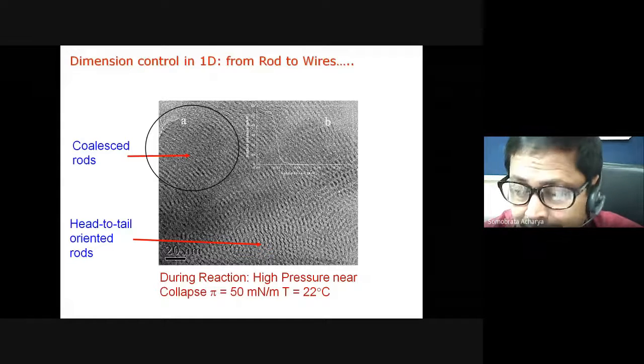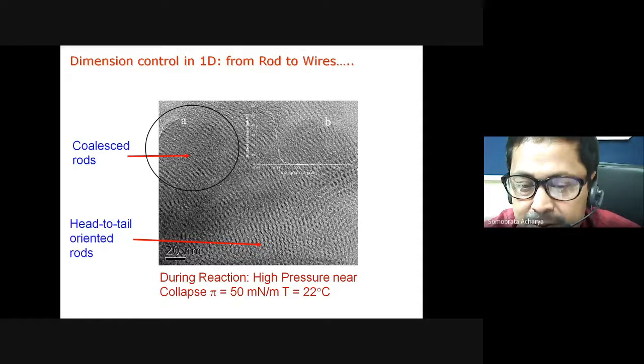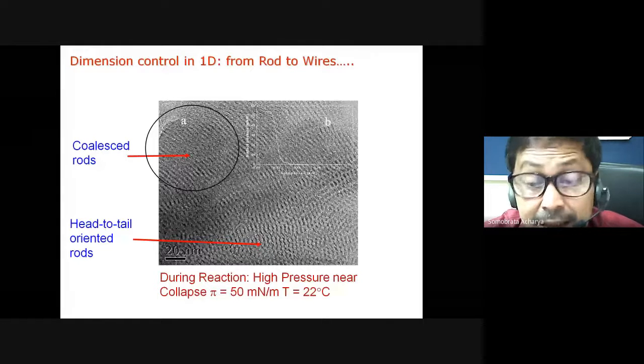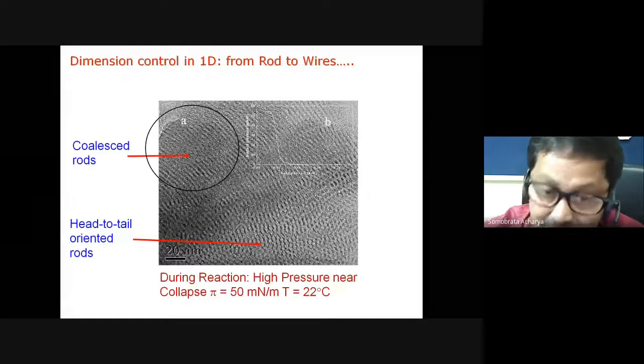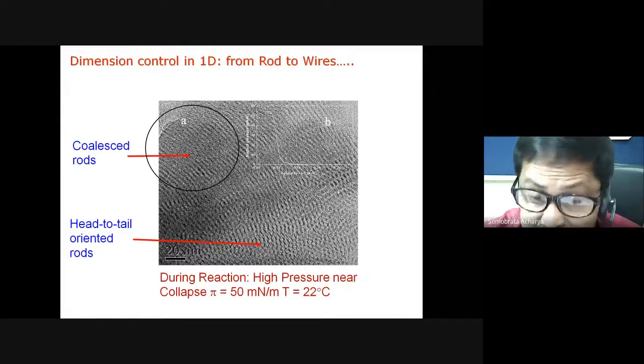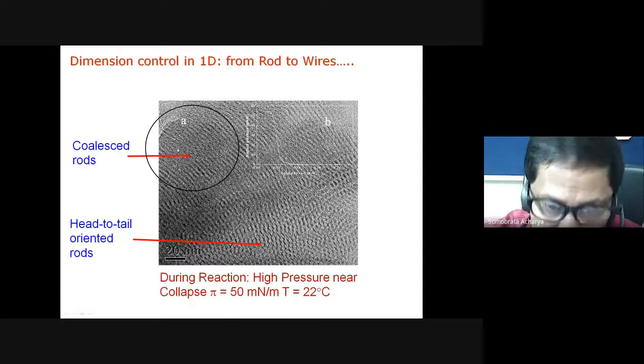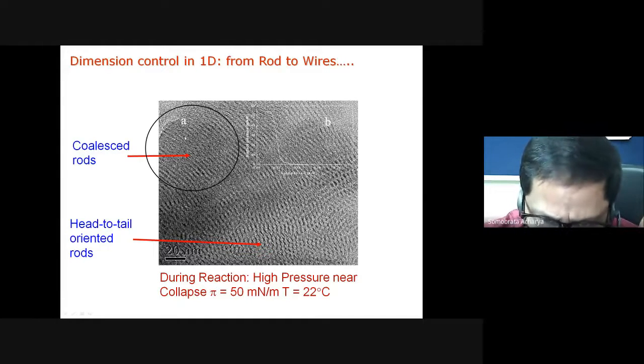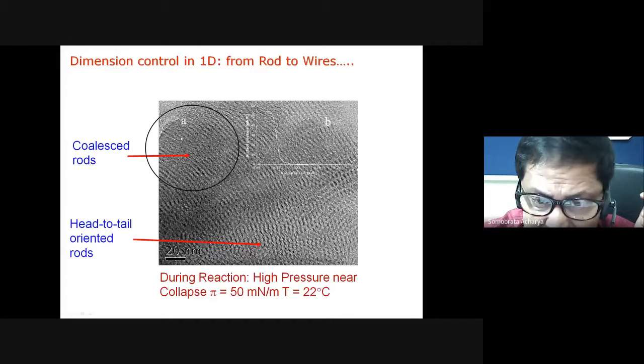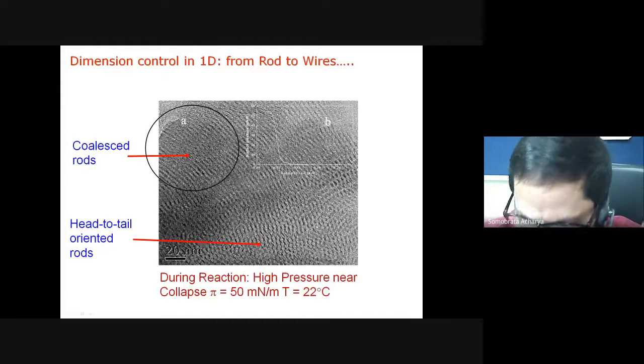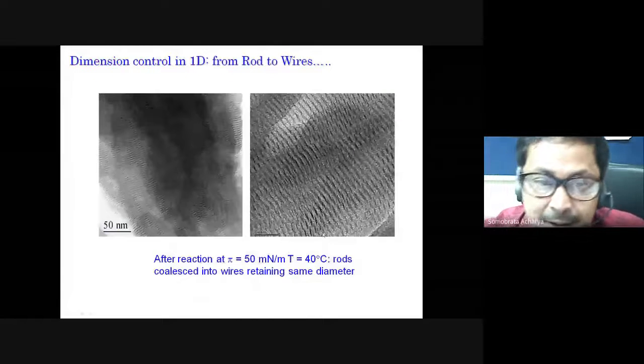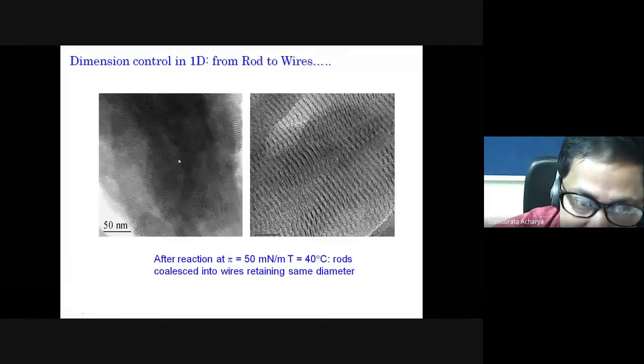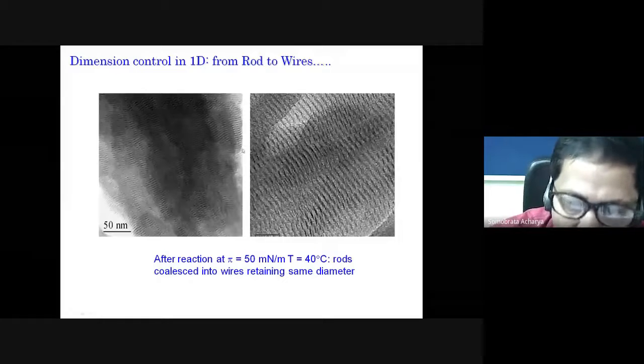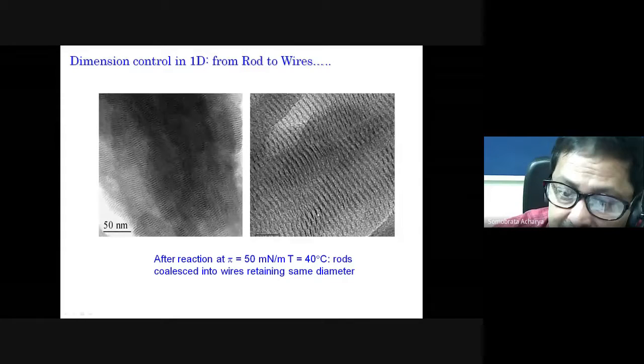So this is a very interesting observation that I have done nothing. I just kept the surface pressure on, and some of these rods are basically turning into nanowires of the same diameter. This is important, retaining the diameter the same. So this circle shows that some rods are already merged or coalesced into nanowires, and the rest of the nanorods are remaining in the aligned form. So now we thought that we should give some kind of heat. So some heat is given to the water surface there, and you see all the nanorods are turned into nanowires retaining the